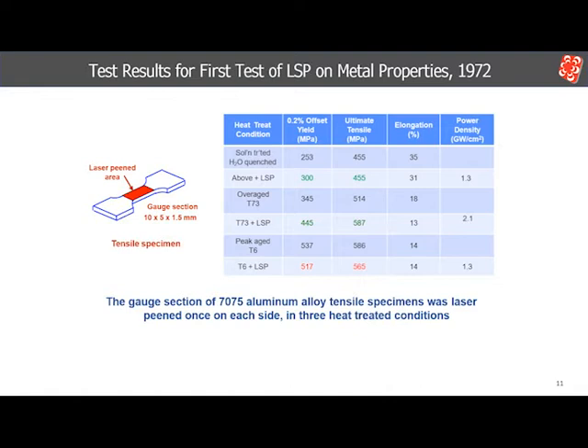The strongest peak aged condition has a very fine dispersion of small precipitates between a coarser dispersion of large precipitates. This imparts a big increase in precipitate strengthening, which is higher than the strain hardening effect. Thus, the shock wave actually causes a slight loss in strength because the dislocations driven by the shock wave had cut paths through the small precipitates. This small experiment showed that a laser shock wave could significantly change the mechanical properties of a metal. Based on this result, Wilcox and Ferrand submitted a proposal to the National Science Foundation to pursue exploring the effects of laser-induced shock waves on metals.